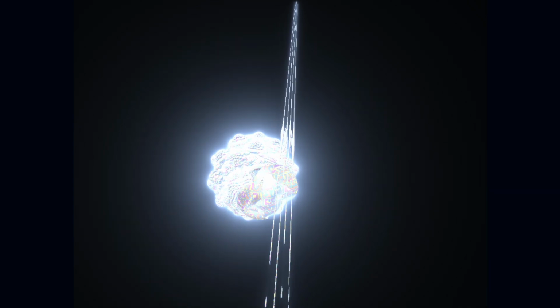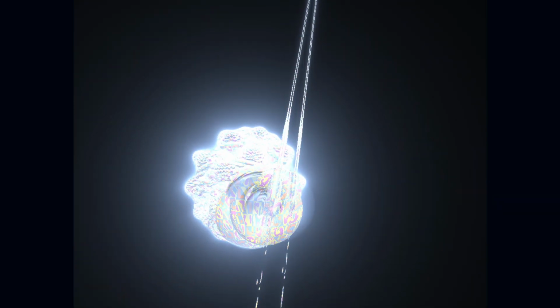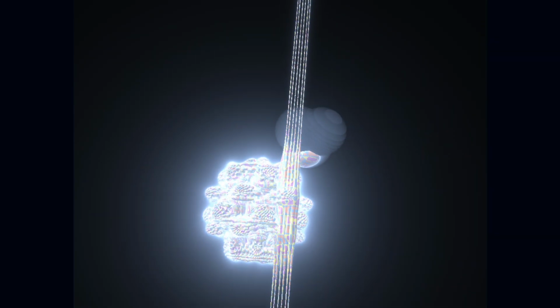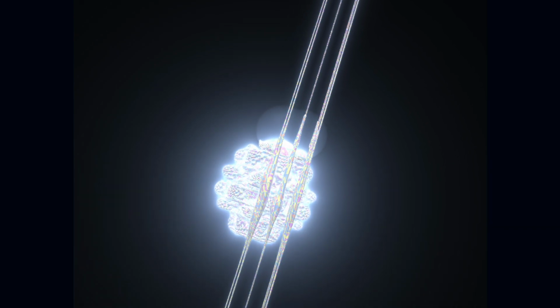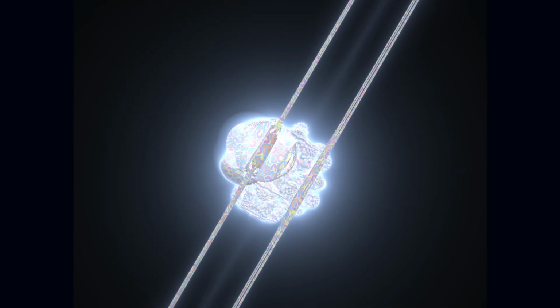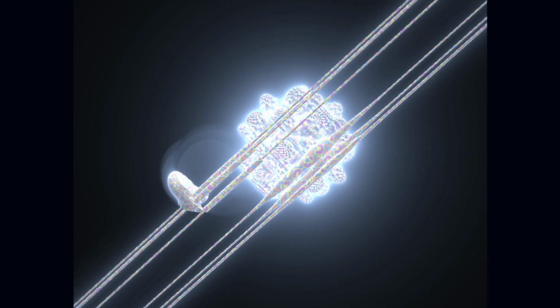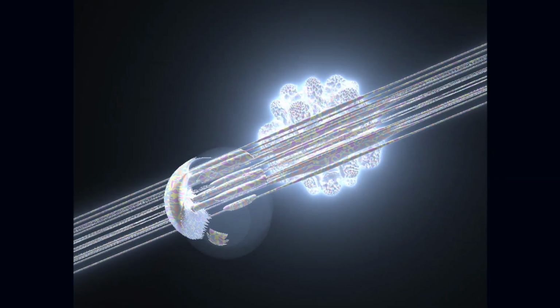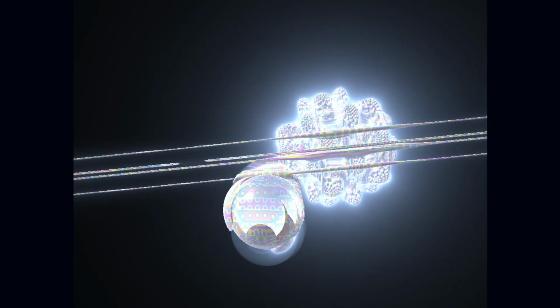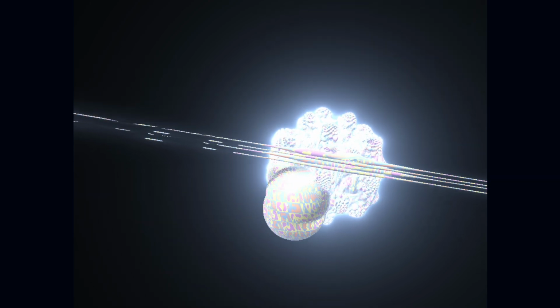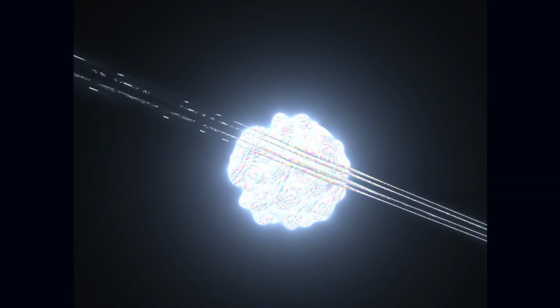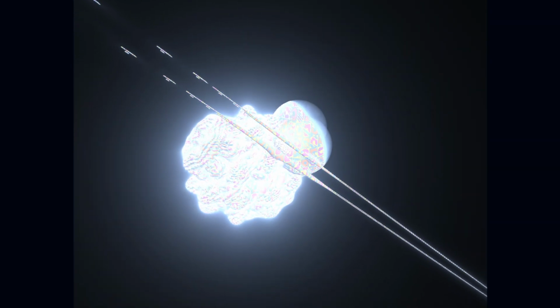Exactly. So this phonon-mediated attraction, this attraction to the positive wake, can actually overcome the direct Coulomb repulsion between the two negatively charged electrons. The phonon acts like a mediator, creating an effective attraction. Precisely. It binds them into a weakly bound pair called a Cooper pair. The Cooper pair, the heart of conventional superconductivity. Absolutely. And these Cooper pairs, being composed of two fermions, behave like bosons. And bosons can do something electrons can't. They can all occupy the same quantum state. They condense into a single macroscopic quantum state. This condensate can then move coherently through the lattice without scattering off imperfections or phonons in the same way individual electrons do. Resulting in zero electrical resistance.